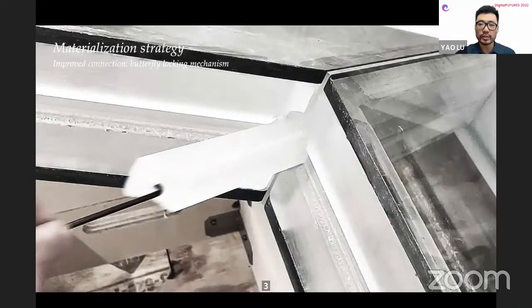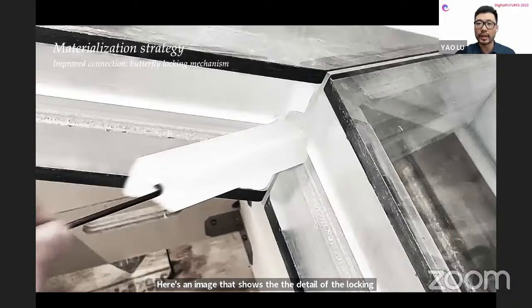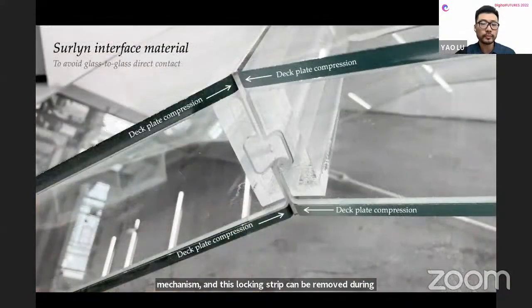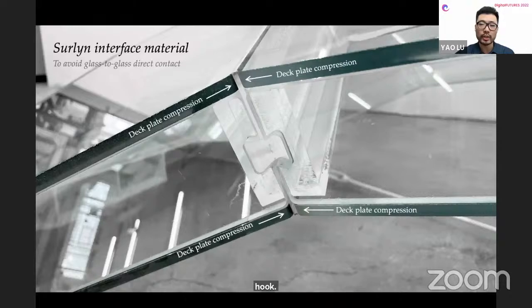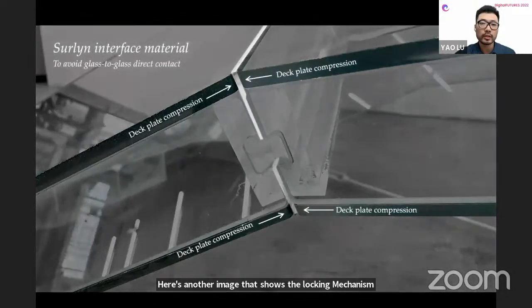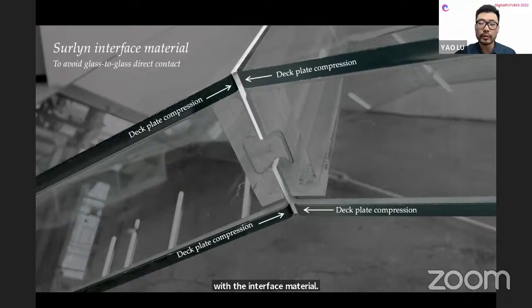Here's an image that shows the detail of the locking mechanism, and this locking strip can be removed during the assembly just simply by a small metal hook. Here is another image that shows the locking mechanism with the interface material. So the compression coming from the deck plates will be passing through this interface, and therefore the material selection of this part will be very critical.